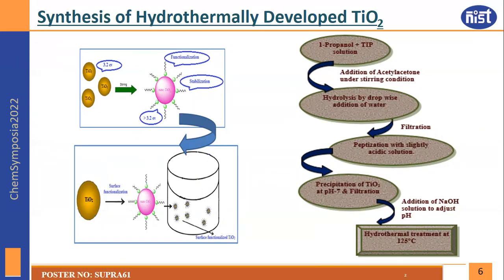After a few hours, the peptized TiO2 was adjusted to pH 7 and it was filtered using filter paper, and it was washed repeatedly to remove all the nitrate groups from the solution. It was again adjusted to pH 11 and it was hydrothermally treated at 125 degrees centigrade, and finally the hydrothermally treated titanium dioxide powder was obtained.